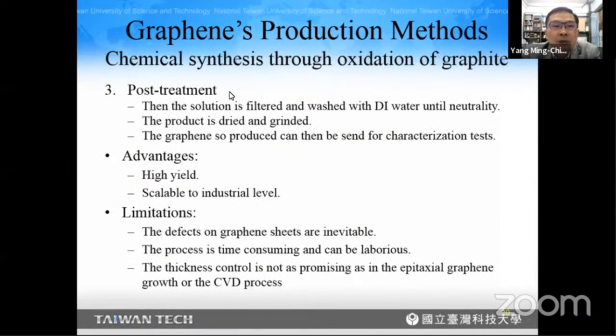And the third step is post-treatment. The solution is filtered and washed with deionized water until neutrality. The product is dried and ground. The graphene so produced can then be sent for characterization tests. The advantage of this method is that it is a high yield process and also scalable to industrial level. And the limitations of this method are that defects on the graphene sheet are inevitable, and the process is time consuming and can be laborious. And the thickness control is not as promising as the epitaxial graphene growth or the CVD process.